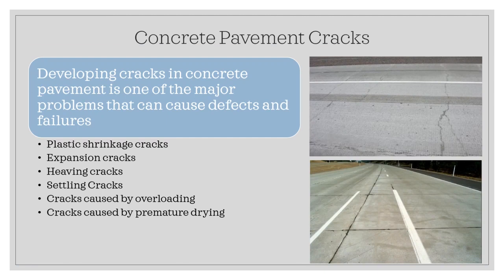Developing cracks in concrete pavement is one of the major problems that can cause defects and failures. There are many different types of cracks in concrete pavement, including the plastic shrinkage concrete crack. When the concrete is still in its plastic state before hardening, it is full of water. And when the water eventually leaves the slab, it leaves behind large voids between the solid particles. These empty spaces make the concrete weaker and more prone to cracking. This type of cracking happens frequently, and it's referred to as plastic shrinkage cracking.